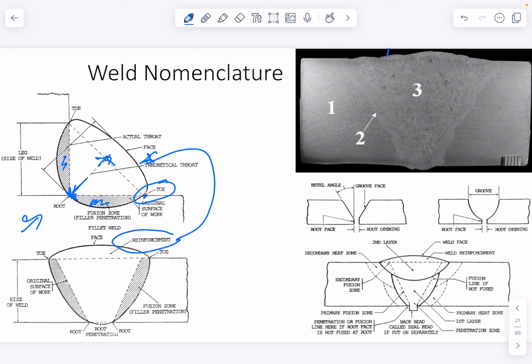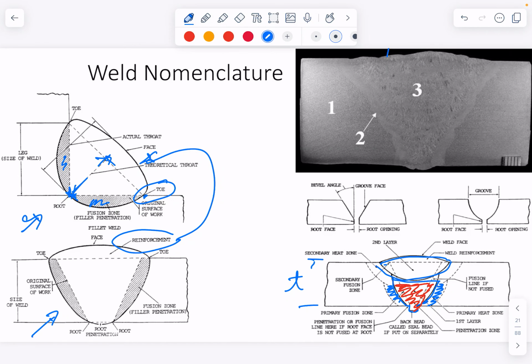So this is obviously a fillet weld, this is a butt weld, same terminology. You will quite often get, if you're doing thick plates, there is a limit to how much weld you can put down in a single pass. So you might end up doing one weld here, and it's got a fusion zone or a heat affected zone out there where you're melting this pool of metal, and then you've got to come back over that and put your second or third or fourth run to get the required thickness.